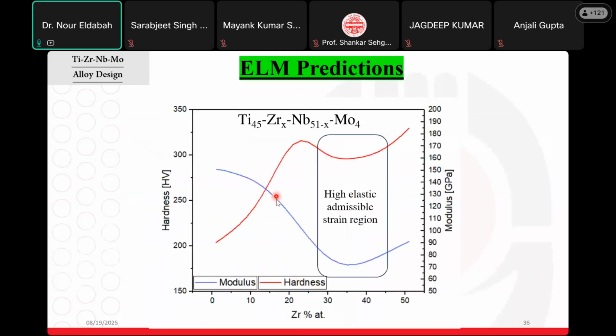We excluded one system, for example, titanium 45, zirconium X, niobium 51 minus X, molybdenum 4, and we can find a region. In this region, we have a low elastic modulus with the blue line and high hardness. This will give us a high elastic admissible strain region, which is a ratio between the elastic modulus and hardness. This is a very optimum alloy that could be used for orthopedic implantation. So your composition should exist in this region to get low elastic modulus with high yield strength.